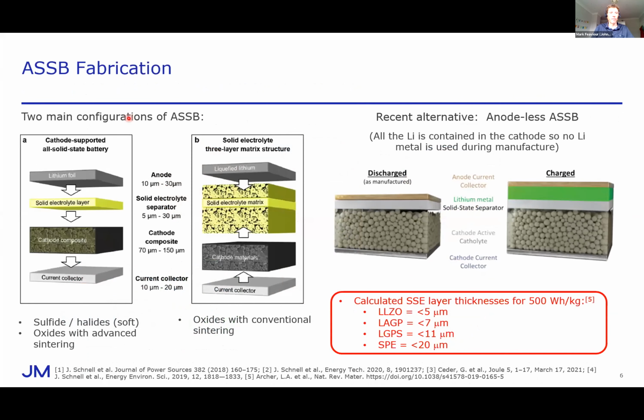Now, I said I wouldn't really talk about fabrication, and that's not changed, but this is a couple of schematics showing the different setups or systems for solid state batteries. But the take home message from this slide really is that the calculated solid state electrolyte layers required for a 500 watt hour per kilo energy density have been calculated, in the densest case, the LLZO case, to be sub 5 microns, which is a considerable challenge, and I think it's one the ceramics community should take up with gusto.